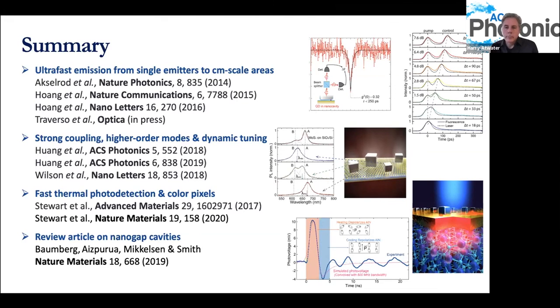The other way that could be interesting is if you have arrays. We have started doing that. A pretty simple way of doing that is by just DPL, or we can do stamps. We have started thinking about making more interesting structures. We actually had one paper where we did a bullseye around emitters and then had a cube with that, so that we could have more control and narrow the radiation pattern even more. And we are thinking about making cool unit cells where you can have more control of the behavior, because we have some light that's lost from non-radiative decay channels. So if you can reuse that in a smart way, that would be very interesting.